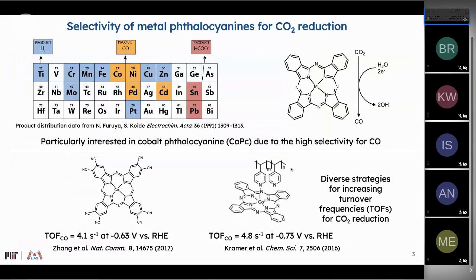So I think it's useful to place this in context. Why cobalt as opposed to any other metal in this ligand framework? One can summarize this with this periodic table that I'm showing here, that if you go too far to the left on this periodic table, one tends to favor hydrogen evolution. This is associated with relatively strong CO binding, and hence these catalysts are not particularly effective for doing CO2 reduction. If you go too far to the right, these are catalysts that favor the generation of formic acid. This may in fact be mediated by plating of the metal out of the catalyst framework. And then there are catalysts in the middle here. Ones based on, for instance, cobalt or nickel. These are catalysts which are relatively selective for converting CO2 into CO. And it turns out that the cobalt phthalocyanine is the most selective among these.